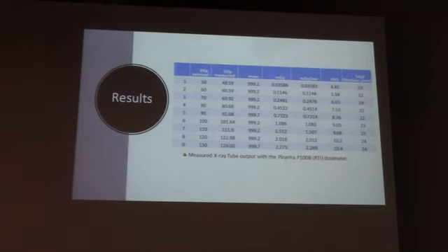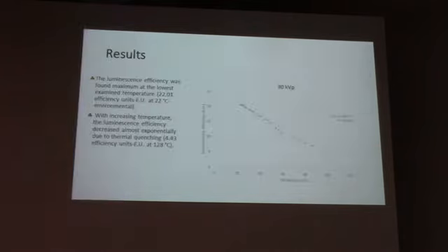These are the results we had. Actually, this is the dose that was coming out of the X-rays. And these are the actual results of the temperature. What we found out is that the maximum absolute efficiency, which translates to the maximum light coming out of the crystal compared to the X-ray photons that hit the crystal, was at the lowest temperature, which was 22 degrees Celsius, and it was decreasing while we were increasing the temperature. The lowest was around 128.